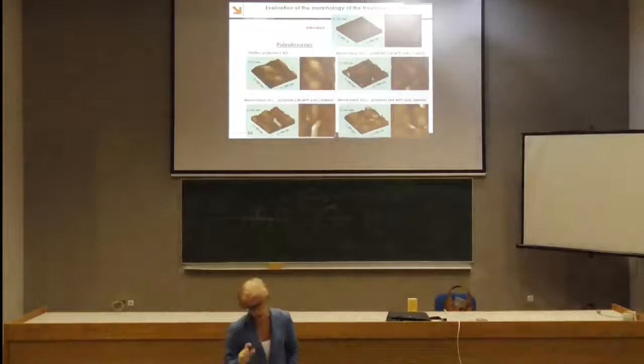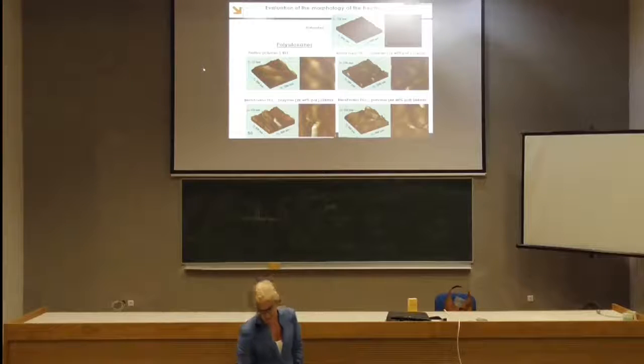Is this one. We have a roughness of the surface that is normal. These are measurements made at the atomic force microscopy, and you have the surface of the marble, and you can see that with the treatment, the blend of the treatment with the nanoparticle, you are going to increase a lot the Z height of the samples, so the roughness of the samples.